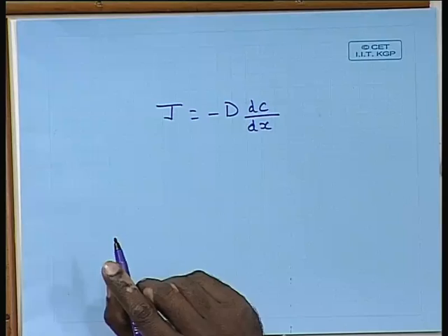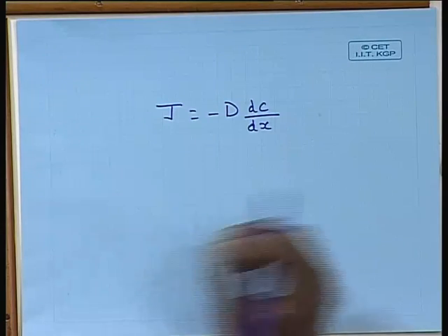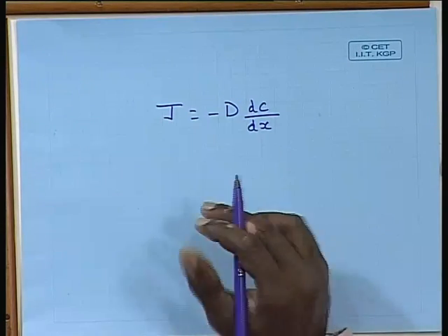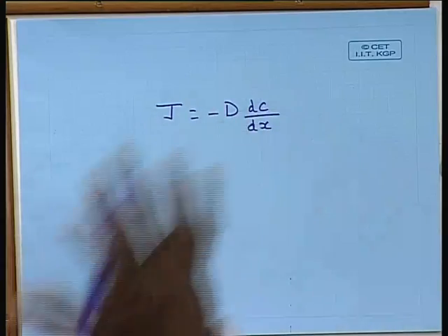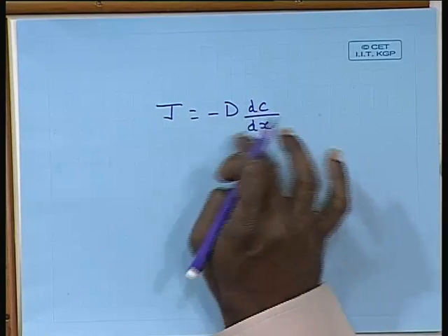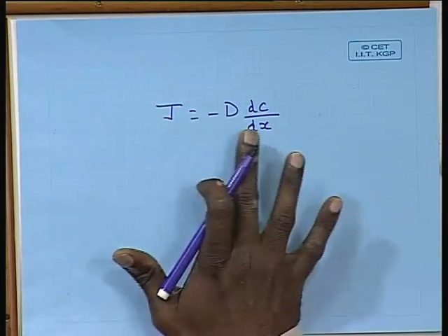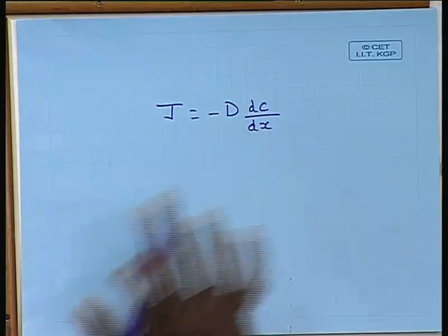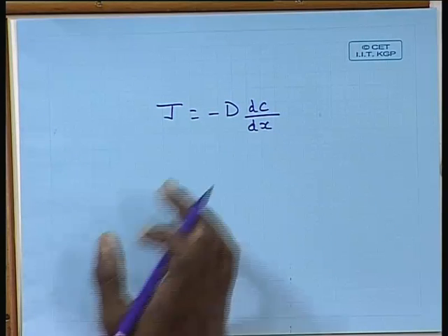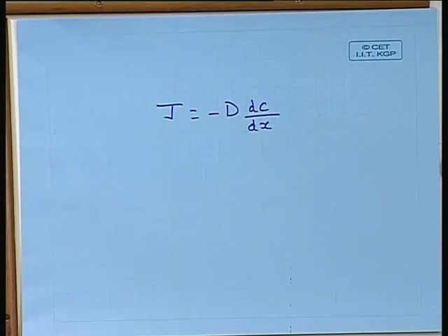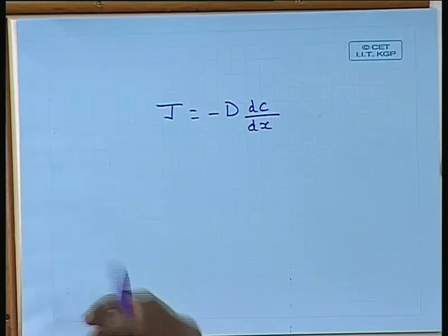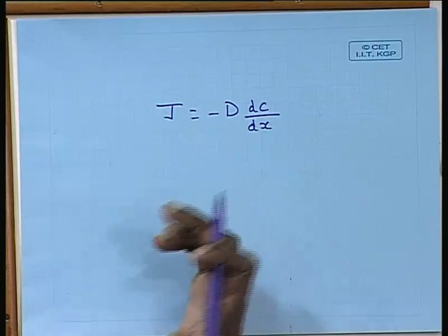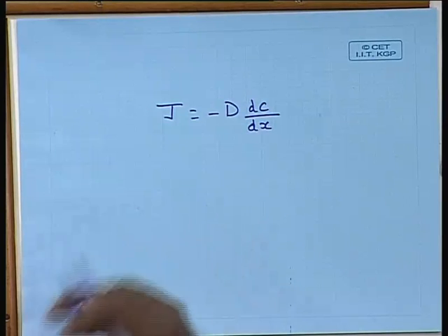So dC by dx is equal to d mu by dx in principle for a binary system, but for a ternary or quaternary system it is not so. So let us consider it is a function of two things. The flux is diffusivity and concentration gradient dependent. So diffusivity depends on the temperature, we all know, and also the concentration, of course, because we can think of diffusivity as concentration dependent or concentration independent when we try to calculate it.